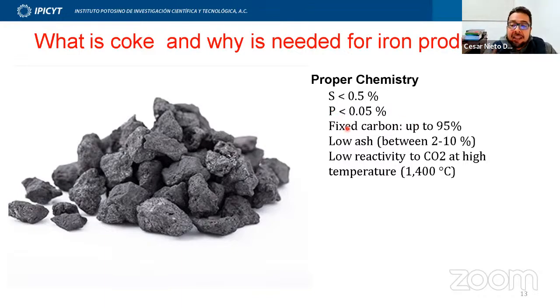Also, it has a very high fixed carbon, up to 95%. Right now, we are working with coke from a company in Europe that has 97% fixed carbon, which is a very high quality coke. Also, it has very low ash. It has to have very low ash because at the end, if you have very high ash, this ash will go to the slag, and is going to be just a waste of material and also of energy, because the slag takes part of the energy inside the cupola furnace.